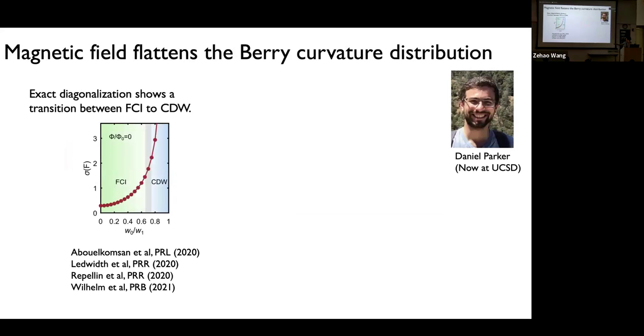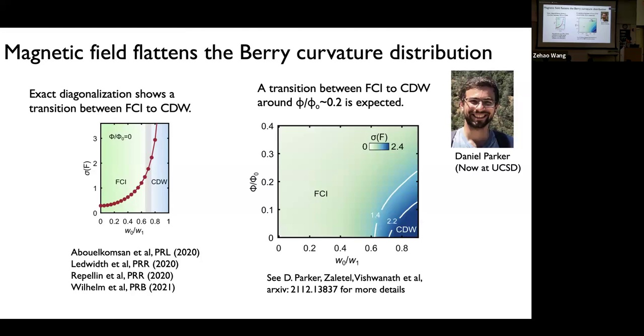Basically, you can look at the exact diagonalization, what ground state you get, and that's how I color this plot. On the left-hand side, you get FCI, and then on the right-hand side, you get CDW. Here, the x-axis is this tunneling parameter between layers called W0 over W1, that's decided by the relaxation. And the red circles are basically data points that you will get if you compute the Berry curvature inhomogeneity of your energy band. And you can try to look at how this changes as you change the magnetic field.